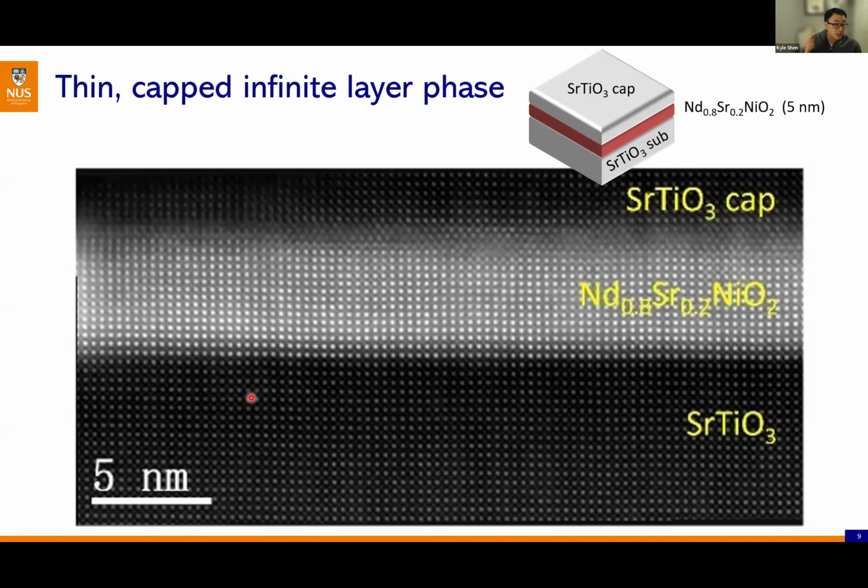And so what we could conclude is that at least in the case of neodymium nickel 2, you only need a very, very minute amount of this impurity phase, on the order of a fraction of a percent, to give the kind of signals that we had seen in some of our ostensibly neodymium nickel 2 samples and what other people have reported as well.